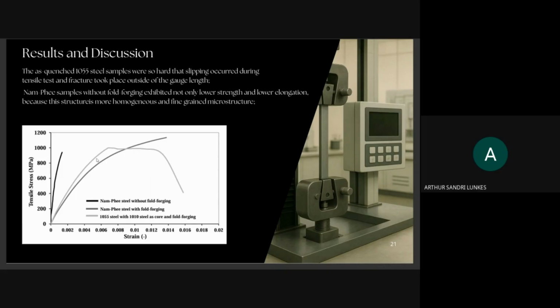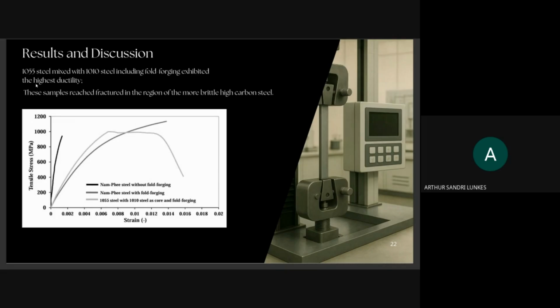But for this trio here, the NP sample without forging exhibits not only lower strength but lower elongation. You can see this line here. With the mixed 1010 steel and 1055 steel, we can obtain the highest ductility, and with the NP steel with fold forging, we obtain the highest tensile stress. All the samples reached fracture in the region of the high carbon steel.